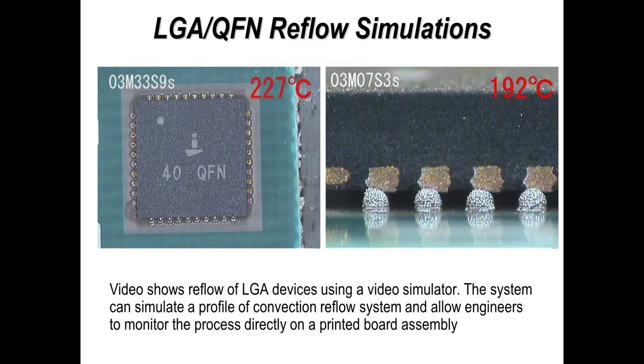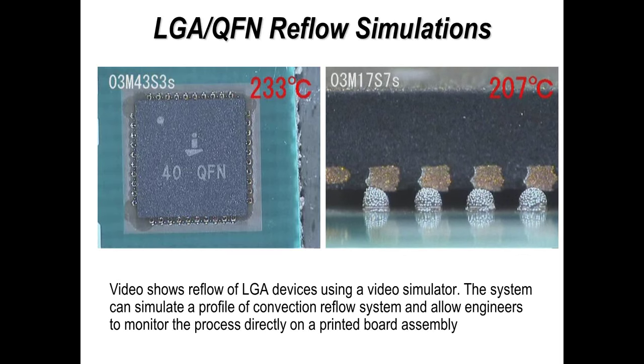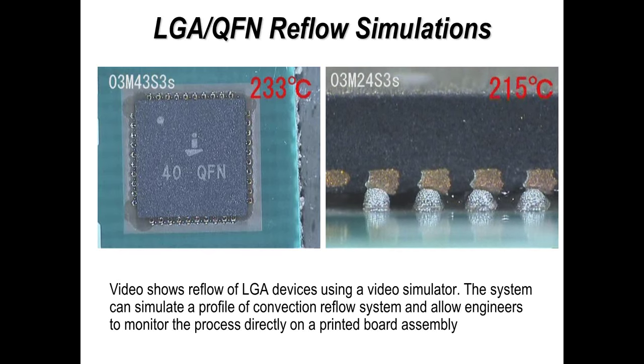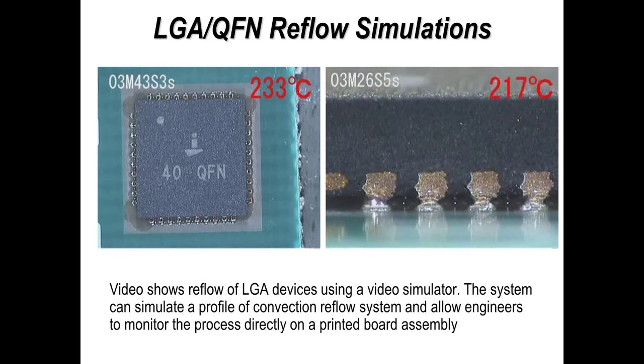Generally speaking, when you look at void formation, it's the volatile material in the solder paste you're seeing. These two video clips that I'm showing online at the moment, one shows the reflow of a QFN, and the second one shows a sideways view of the QFN. And when it gets to reflow, what you'll actually see is the volatile material, which is basically the liquid, the gelling agents of the solder paste, visible.